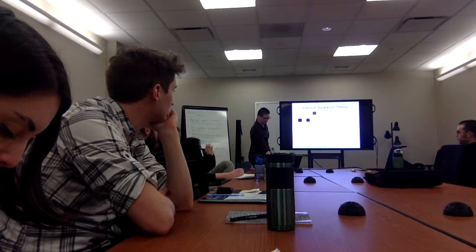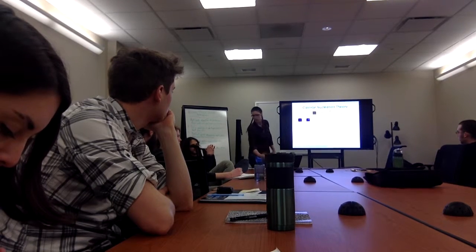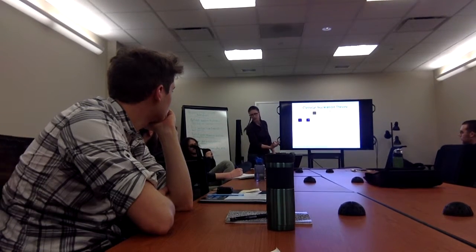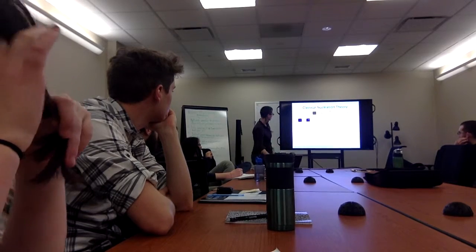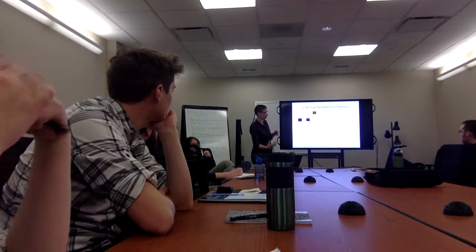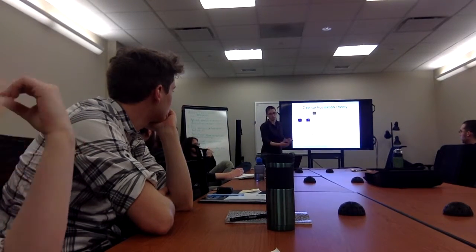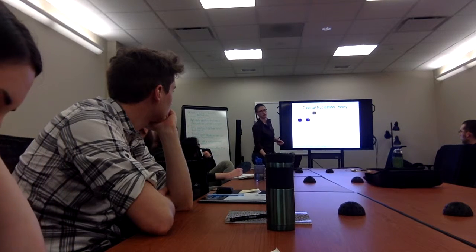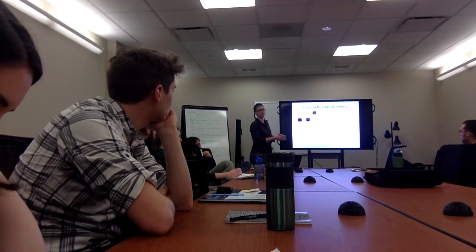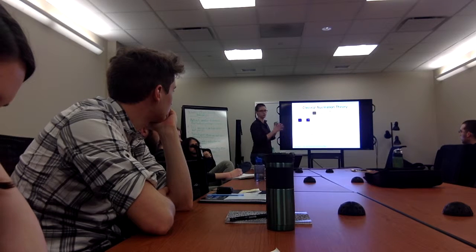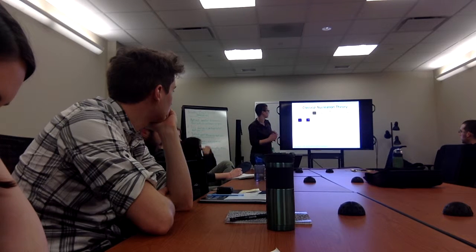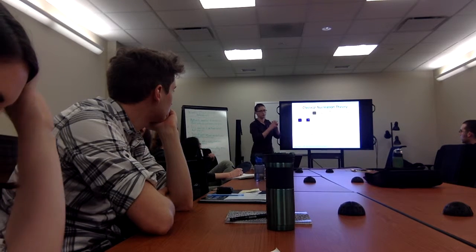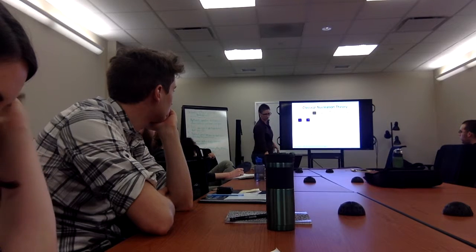Also neglect curvature effects of the interfacial tension, and that's what you mean by the gamma being constant. Gamma is constant over the area, and doesn't change as the nucleus grows. So these are the assumptions made for classic nucleation theory. The classic nucleation theory refers to the state where you're making these assumptions. Everything's nice and uniform everywhere, everything's continuous, and the values don't change as the nucleus grows.